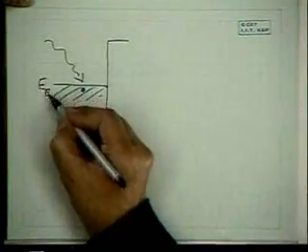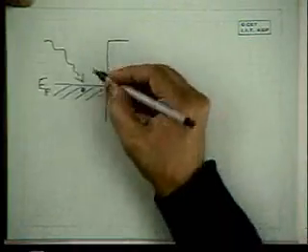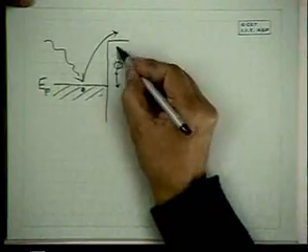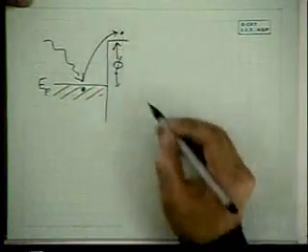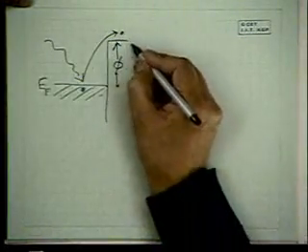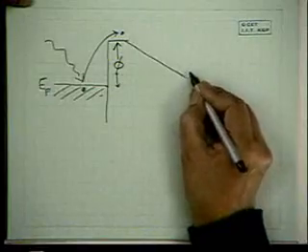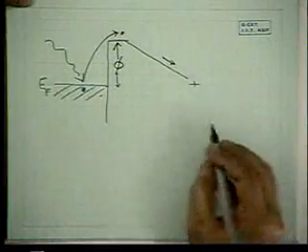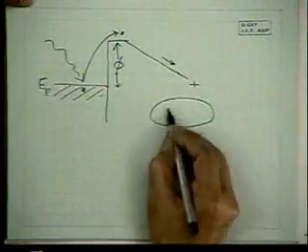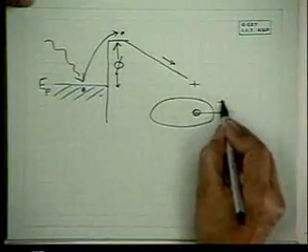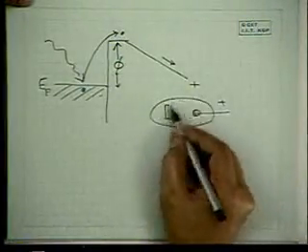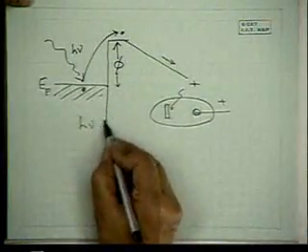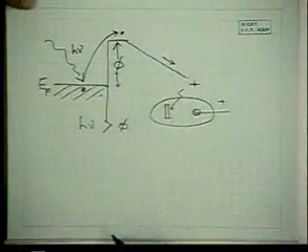If it's a metal, electrons at the Fermi level can be excited, and if they can overcome the work function, the electrons are emitted into vacuum. And for example, if there is an electrode here which is at positive charge, they'll be collected. Typically, a device will have an electrode, and this is a photocathode in which the light is incident, and obviously h nu must be greater than phi.